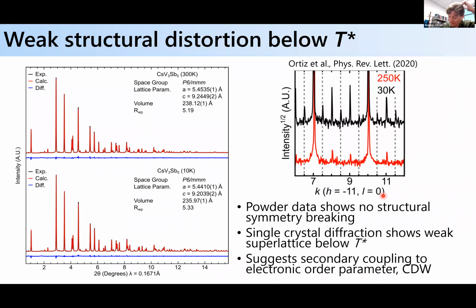Okay, so structurally, if we look below this T star transition, again in the cesium system, this is the room temperature structural refinement, and you look at the 10 Kelvin structural refinement. So this is above and below this 94 Kelvin transition. In a powder average structure, you basically see no change, okay? There's no structural distortion that can be resolved.